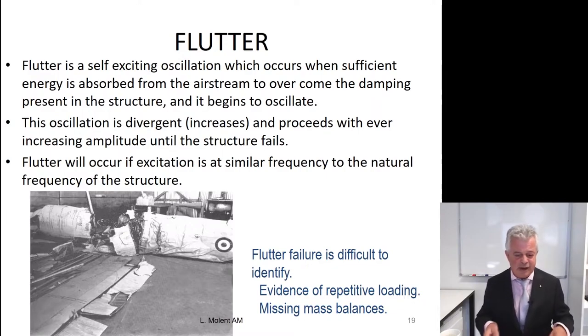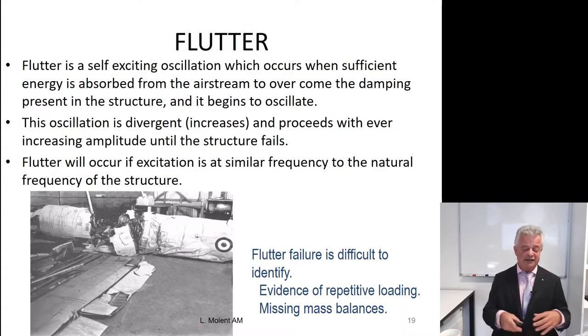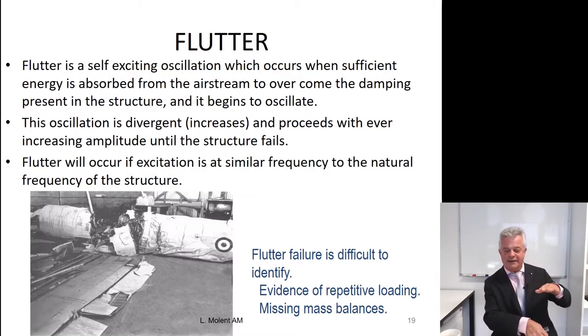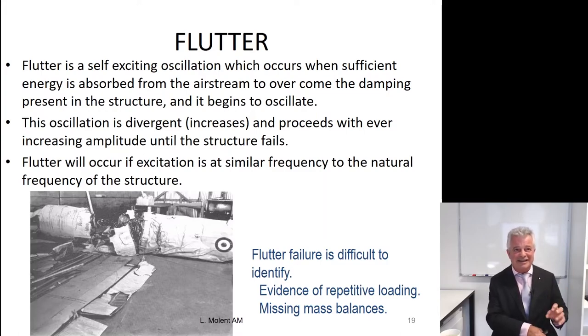And moving on, we'll talk a little bit now about flutter, aircraft flutter. Many things will flutter, but aircraft in particular. It's basically a self-exciting oscillation, which occurs when there's sufficient energy put into the system that overcomes the natural damping that the structure normally experiences. Most things behave in this manner. You get a ruler or a beam and you hit it, it will vibrate, but it will dampen out. Now, if I put enough energy into the system, rather than damping out, the oscillations become divergent, or they increase, and they increase at ever-increasing amplitude, and the structure will fail, okay? Problematic. Flutter will occur if the excitation, and excitation can be due to the airstream or by other pilot-induced maneuvers, is at a similar frequency to the natural frequency of the structure.